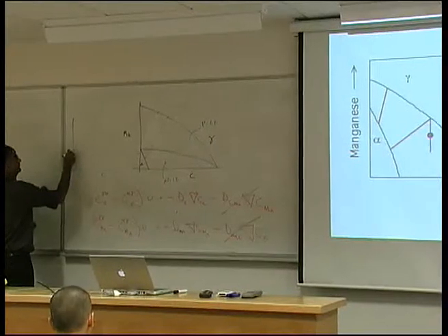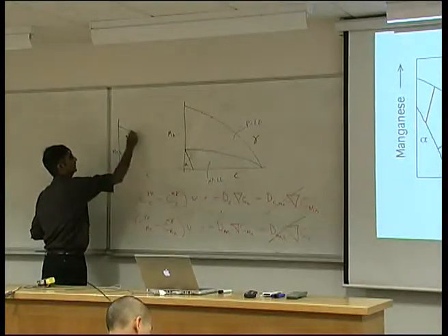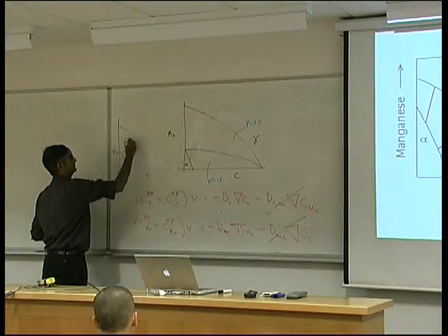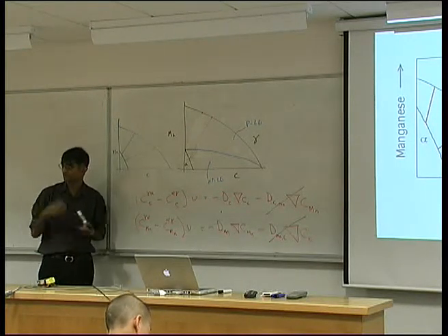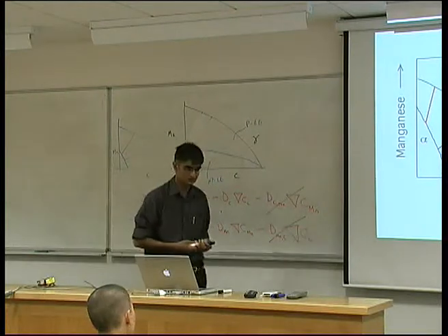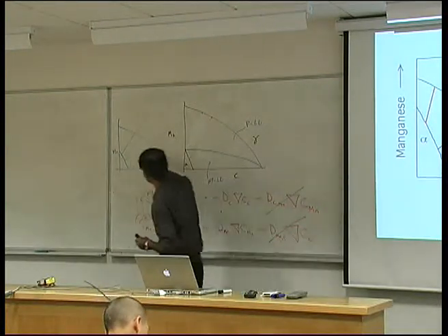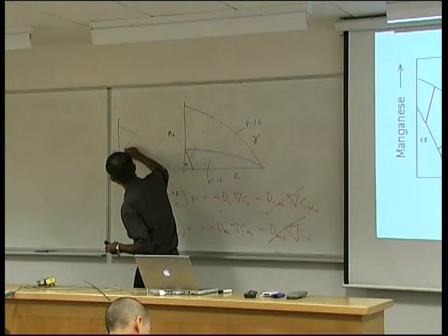Carbon, manganese, and I've got a series of tie lines here, which I've obtained using thermodynamics. Okay. So, getting equal chemical potentials. If I draw right-handed triangles on each of these tie lines,